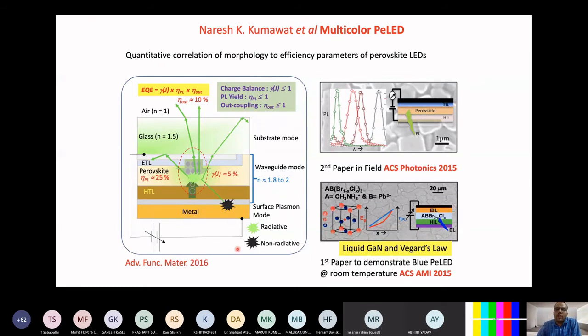semiconductor. And we also demonstrated how the efficiency of this perovskite LED changes with respect to the morphology of the thin films. So a quantitative correlation of the morphology to the efficiency parameter was described in this Advanced Functional Materials 2016 paper, where we showed how the charge carrier balance, the photoluminescence yield, and the outcoupling efficiency all matter together to decide what kind of efficiency can be achieved from the perovskite semiconductor.